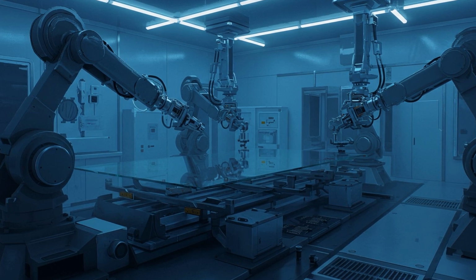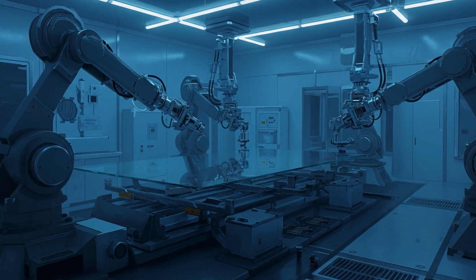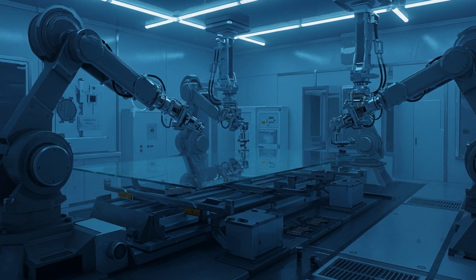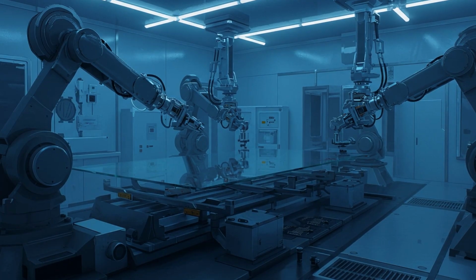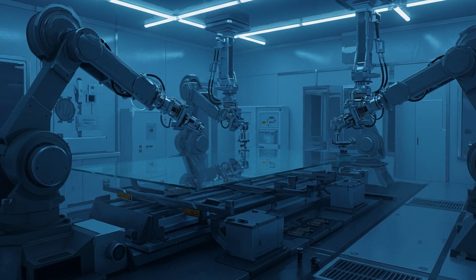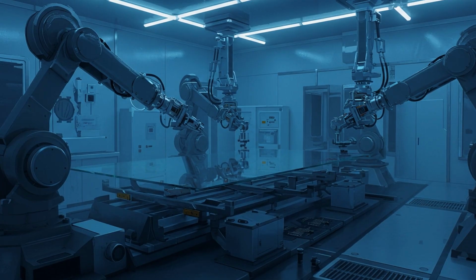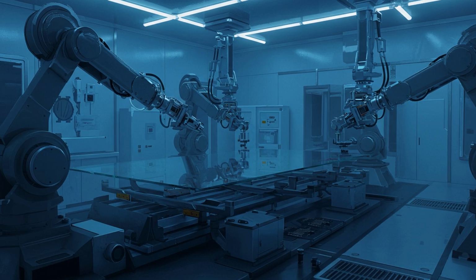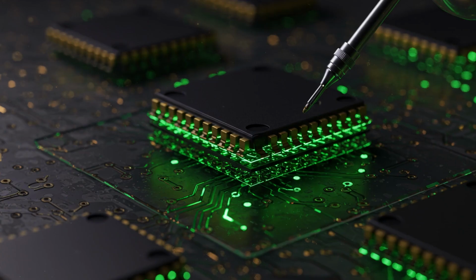It is blasted with deionized water, scrubbed with ultrasonic waves, and treated with ultraviolet ozone to strip away every last organic contaminant. At this stage, the factory environment is a Class 10 cleanroom. This means there are fewer than 10 particles of dust per cubic foot of air. For comparison, the air you are breathing right now contains millions of particles. This level of sterility is non-negotiable, because at the scale we are building, a single skin cell is like a mountain blocking a highway. Once the substrate is chemically pristine, it is ready to become the nervous system of the display. To control millions of individual pixels, we need a massive network of switches.